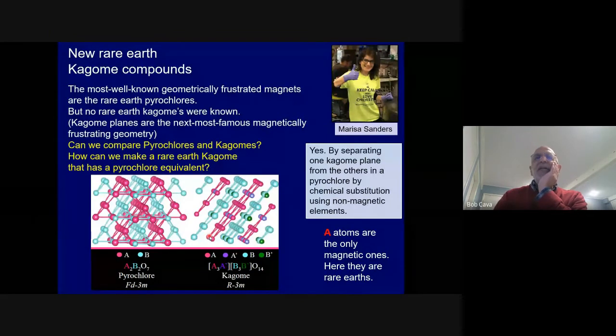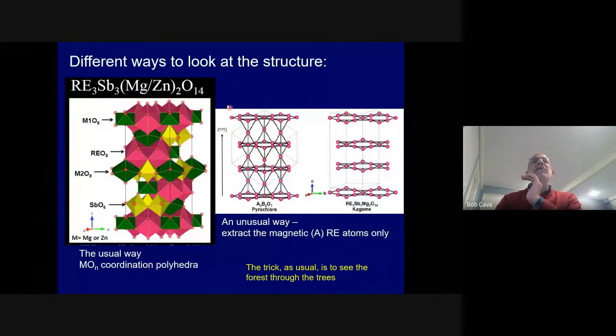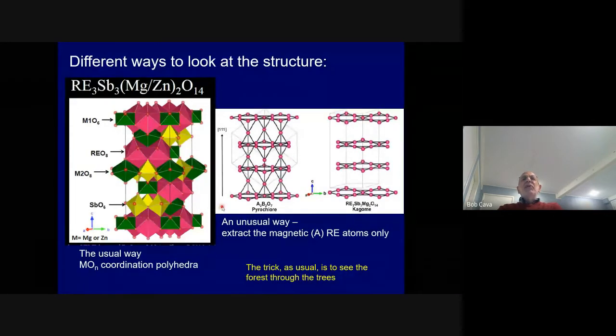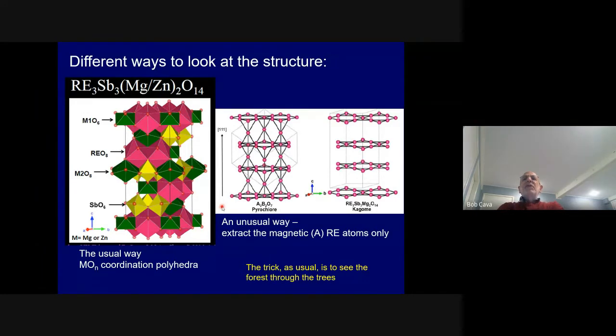So I think the next slide is the relevant one. In solid state chemistry, we typically draw crystal structures this way, which show the metal oxygen polyhedra. And this is the material that this graduate student found, rare earth 3, antimony 3, magnesium 2, O14. And this was a known substance before, but it had been looked at this way, which shows the metal oxygen polyhedra, which is a good way to think of this if you're a solid state chemist. But if you're interested in the magnetism, the thing to do is to take all the confusion out of the picture and just reduce it to just the magnetic sublattice.